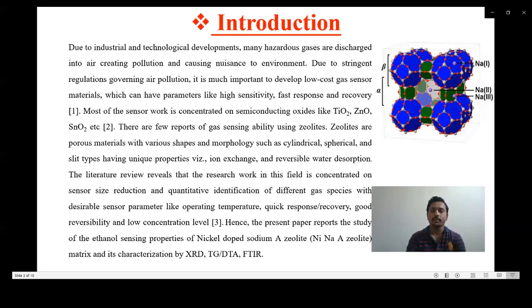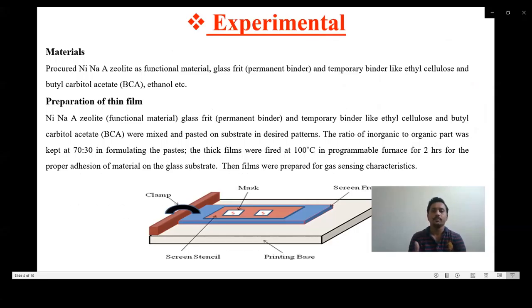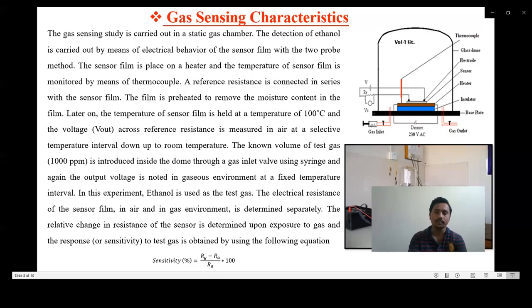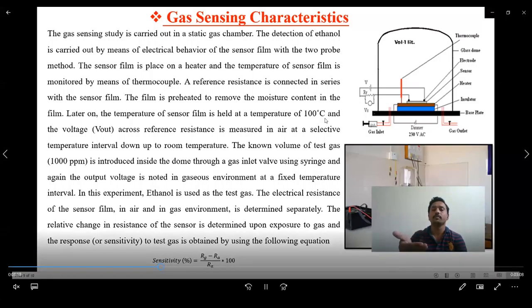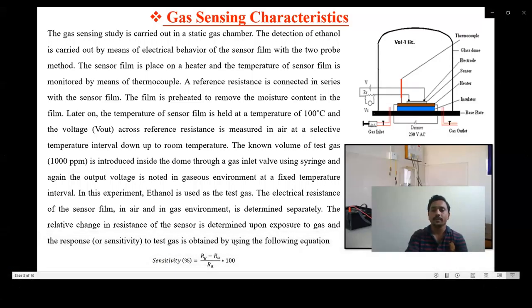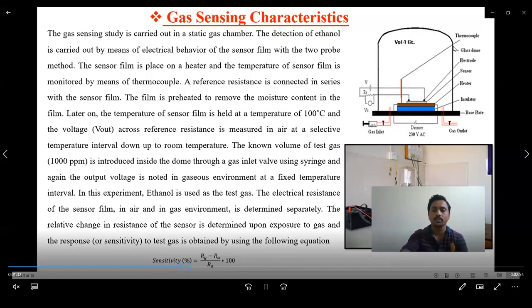That zeolite material we can characterize by XRD and TG-DTA. The zeolite material is made into a thick film with the help of screen printing. The sodium zeolite is the functional material, and the other material, the binders, are mixed, and they make a film. This film is then fired at 100 degrees Celsius and used as the sensing unit. As the operating temperature increases, we measure the resistance, inject the gas, and again measure the sensing characteristics. This is the domestic-use gas sensor unit.